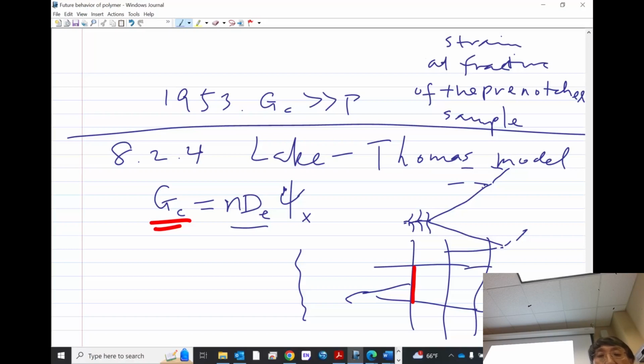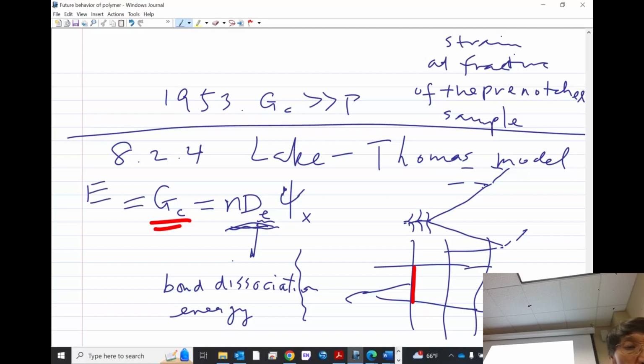Each bond will store energy of the so-called bond dissociation energy. In fact, this is the familiar symbol we used before. Each bond does that. And a strand of n such bonds will result in an energy release of n times d. And remember, this is energy per unit area.